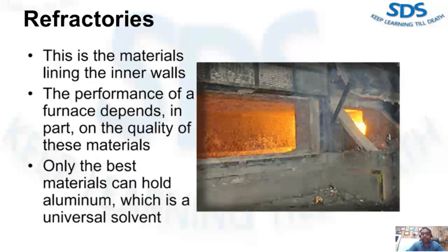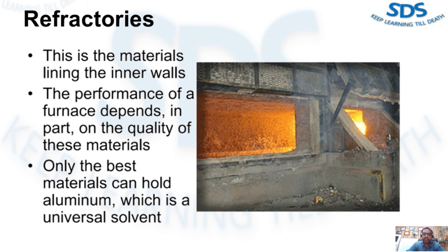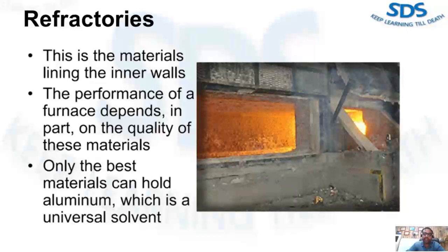Insulating castable or brick is made from various fire clay and aluminum silicate materials such as mullite, but with a much higher degree of porosity than a dense castable or hot-face refractory material. The lower density reduces heat transfer. When utilizing a furnace lining with an insulating castable, care must be taken not to erode or damage the hot face away, as this exposes the backup lining resulting in greater wear and aluminum penetration. This causes accelerated deterioration of the entire refractory, which in extreme cases would lead to liquid metal breakout — a very dangerous situation.